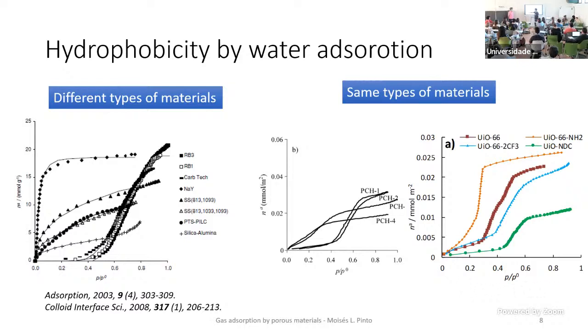You don't have any adsorption of water in here. Then it increases like this. And then you have other materials that stay in between. They are not so hydrophilic as zeolites and not so hydrophobic as activated carbons. So we can also use molecules, like probes, to see what is the chemistry of the surface.